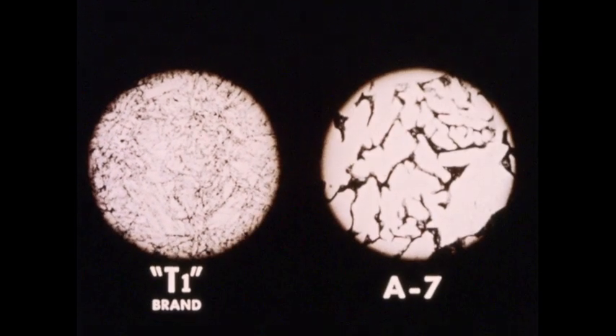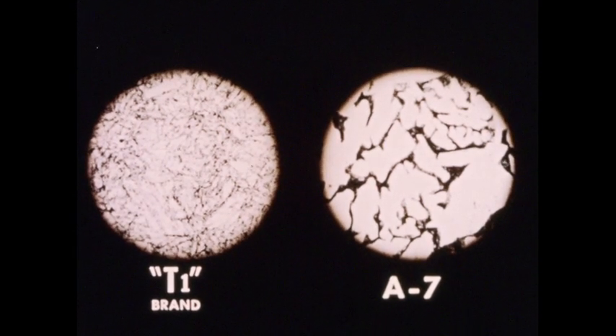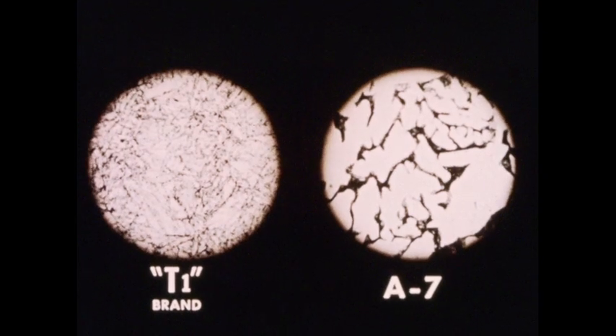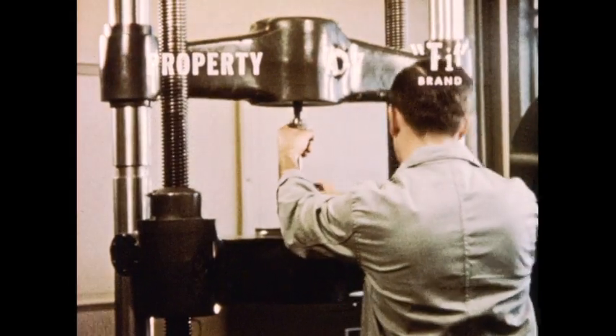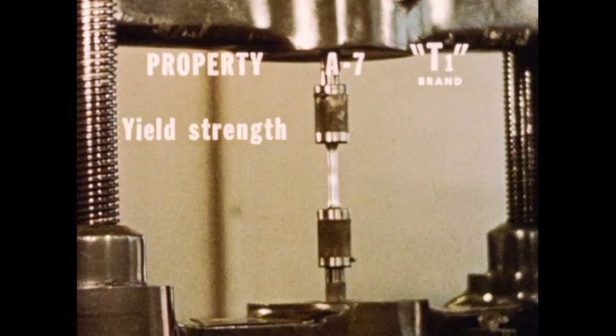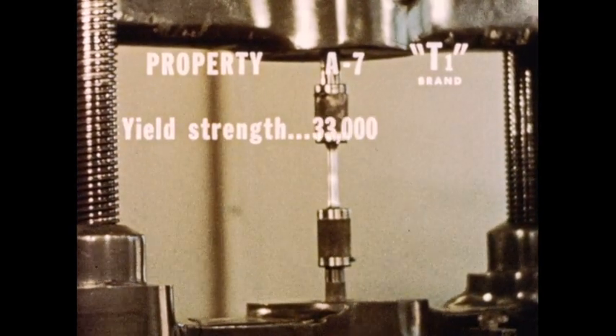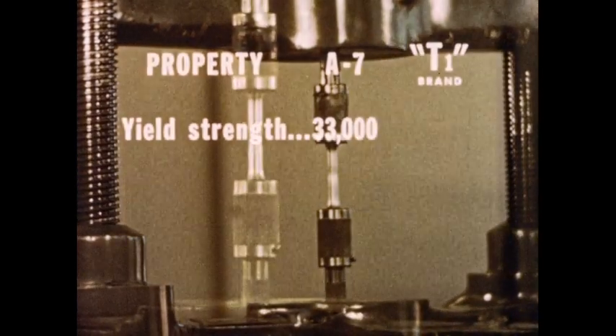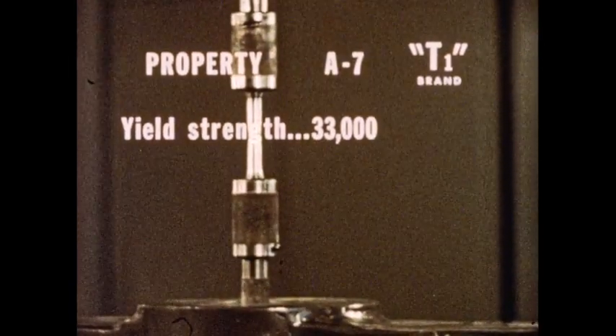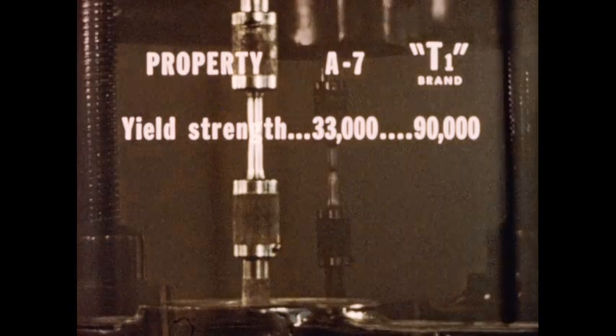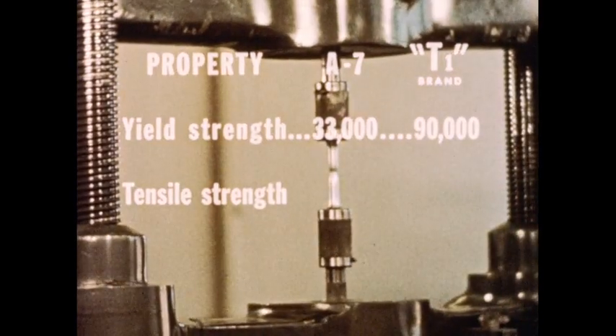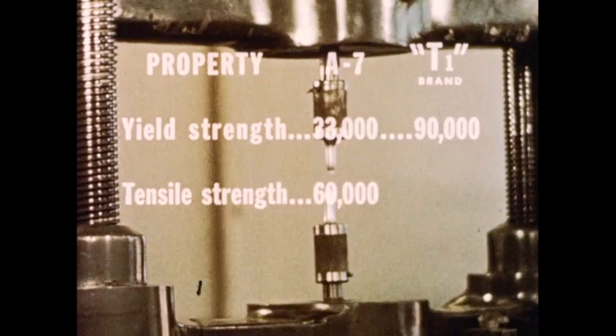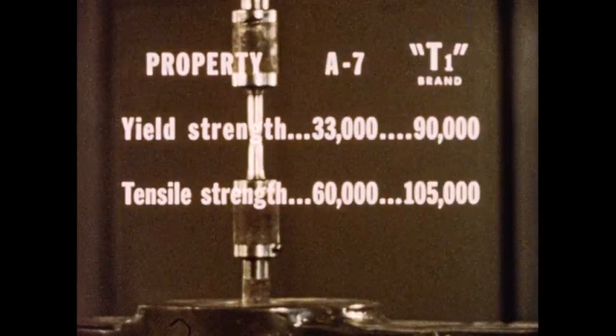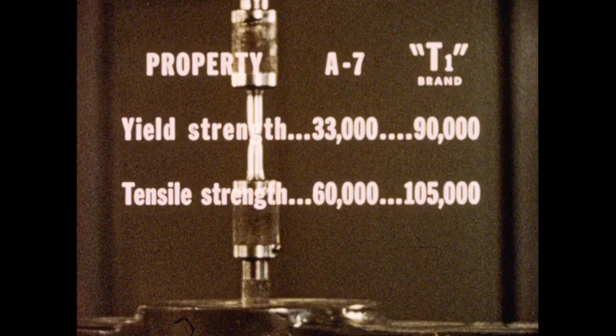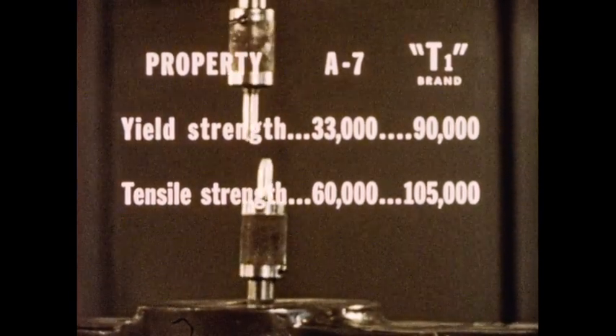Note that there is a distinct difference in the microstructure of T1 as compared with A7 carbon steel. The effects of the difference are quite impressive, especially in mechanical properties. Yield strength of A7, 33,000 psi. T1's yield strength is almost triple that, 90,000. Tensile strength of A7, 60,000 psi. T1 with 105,000 psi registers 75% higher.